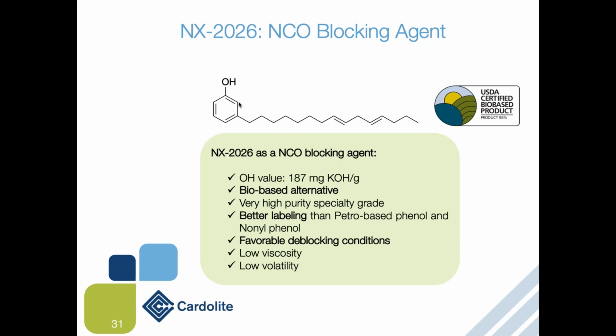And in some cases, having this group and the aliphatic chain can also give you a surfactant effect. Now, some other key performance we have shared here is that when you use a cashew nut shell liquid-based product, we have shown better chemical resistance, like alkaline resistance, and better compatibility as well. All this achieved performance, we believe, comes from the structure itself in comparison to other feedstocks.